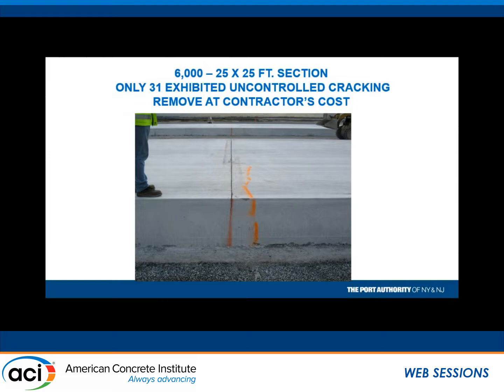31. Almost half of those were in one night's work where they forgot to cut the control joints. If you don't cut the control joints quickly, you're going to get cracks. Okay? So the moral of the story here is we kept the water down, we kept the aggregate large, we maximized the aggregate, we minimized cracking.